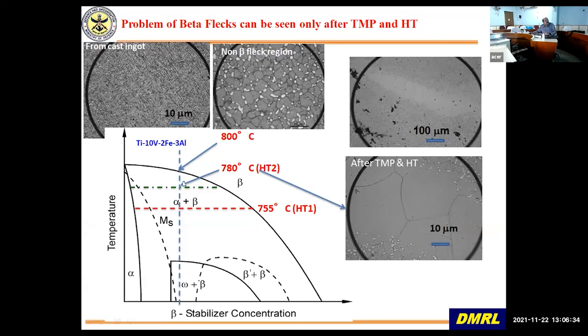Now, why this happens is because when you heat treat just below the beta transus, which is around 800 degrees centigrade, you have to heat treat around 780, 770 or so, because you also want a good combination of fracture toughness. If you go too much below, you will have too much primary alpha and you will not get very good fracture toughness. So that also we optimize. So around this point, in the local region, the beta transus, as you saw, is lower as compared to the other region. So this crosses the beta transus temperature, and you get big beta grains as compared to the other region. So that is the problem if you have this beta fleck problem.